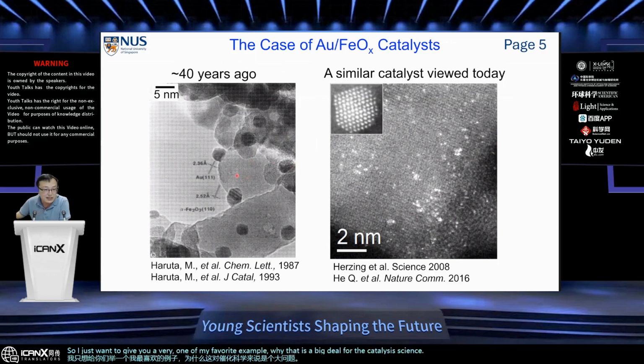As you can see on the left-hand side, this is gold nanoparticles supported on iron oxide, and this was developed around 40 years ago by Professor Haruta from Tokyo. So why is this a big deal? Because gold is typically considered an inert metal, and it doesn't really react with oxygen or hydrogen, so from the catalysis point of view, it's kind of useless. But then Professor Haruta discovered that if you make gold small, if you make gold nanoparticles, they can be the best catalyst for many important reactions.